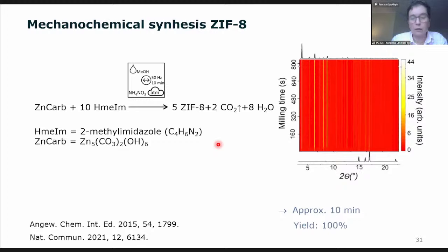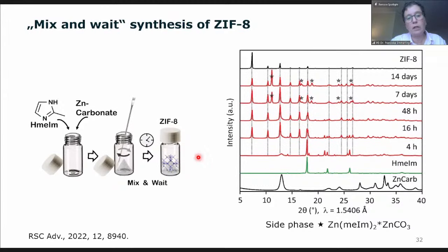And he realized that you don't have to mill at all, so you don't really need to grind the material before. You can also just mix the ingredients and wait. And that's what he did here. You can see again, we have the linker material and the zinc carbonate, and he just waited a bit and got the final product in the end just by waiting. You need a certain time for the conversion here, around let's say 16 hours. Then you get the traces of ZIF-8.